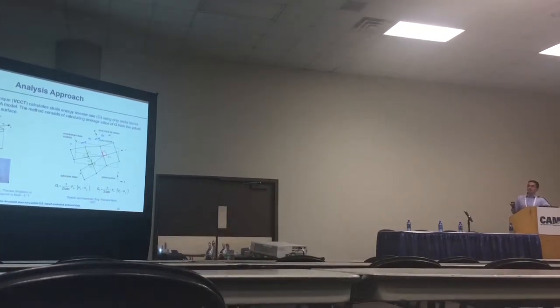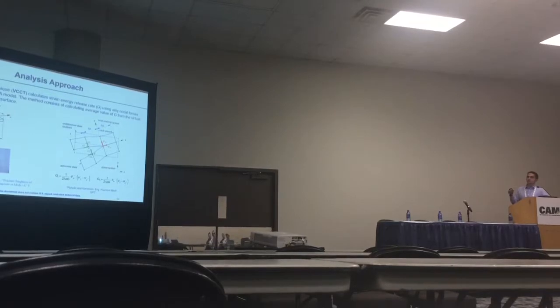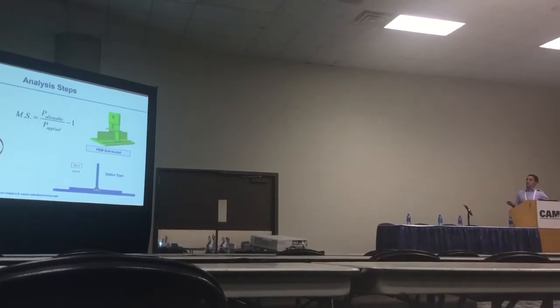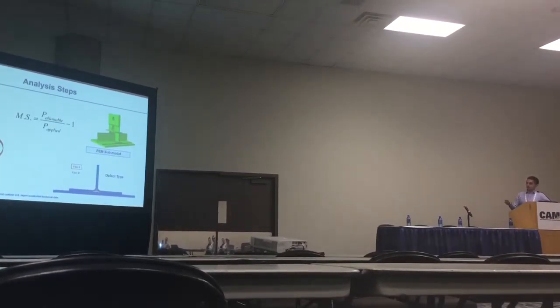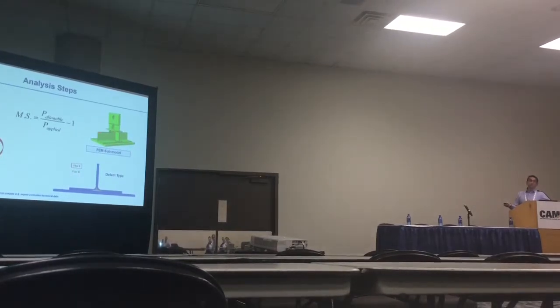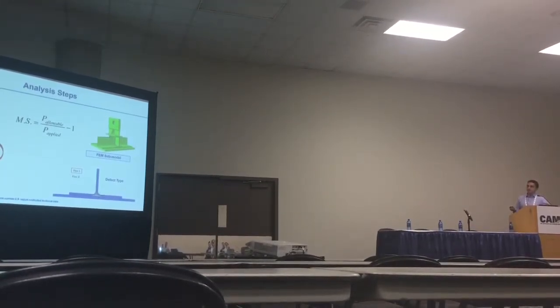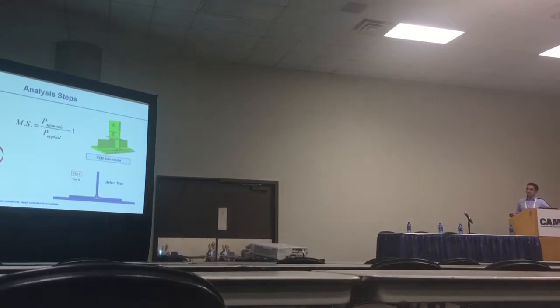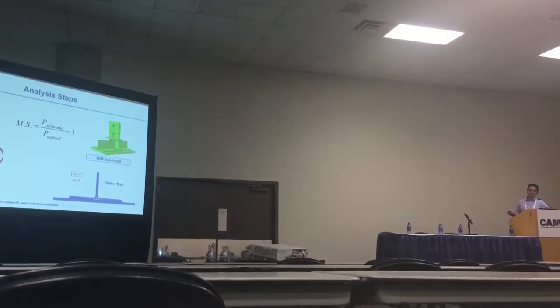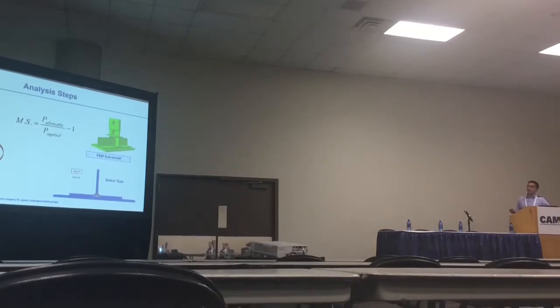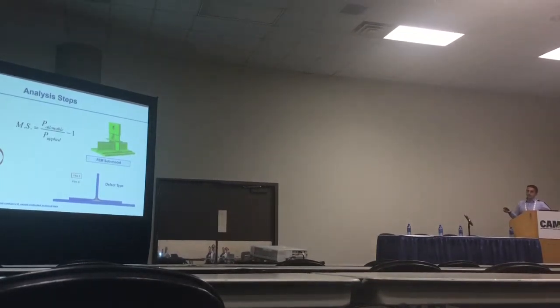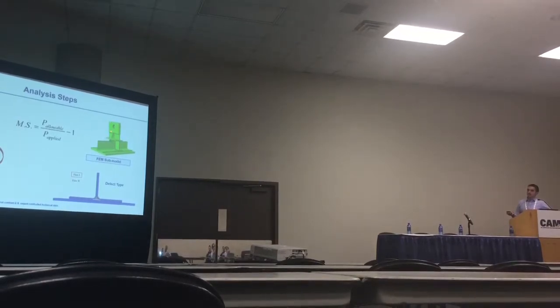The first node release correlates to a fracture mechanics quantity, which is the strain energy release rate of that specific laminate. With all that information, you can then use a simplified element test. As I explained earlier, what you're seeing here is a typical element test. This is the finite element model that I created. It's a blade stringer on a composite skin, and we are doing a pull-off test. The pull-off test is a typical mechanical loading that a wing structure would see. It's like pulling on it in this direction.